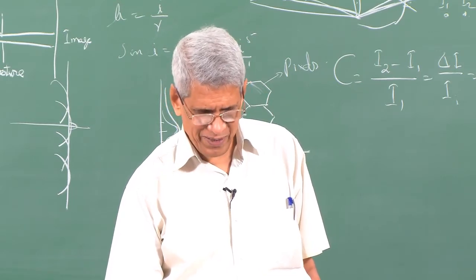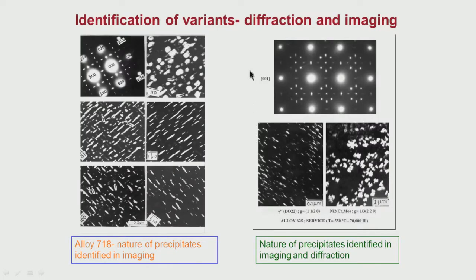If one understands the transformation taking place in the material and the crystallography, an experienced electron microscopist, looking at the diffraction pattern, will be able to make out which are the spots you should use for getting a dark field image.